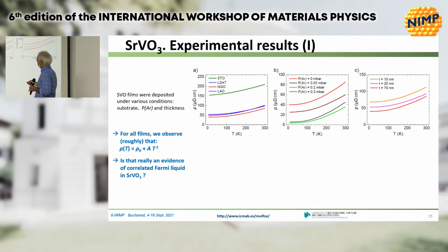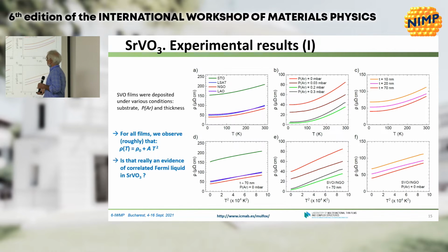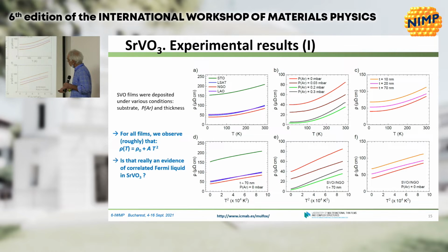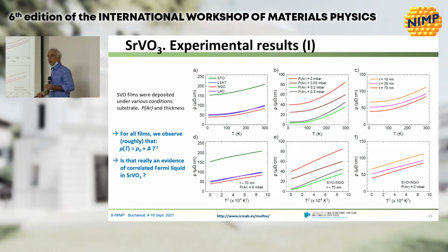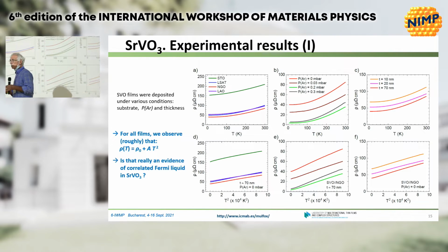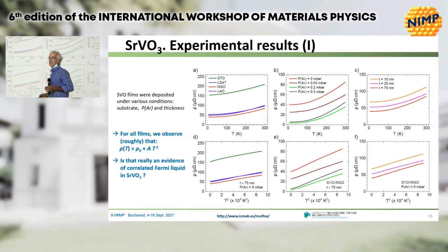This is the resistivity versus temperature of films of a given thickness on different substrates. This is the plot of the resistance on a given substrate as a function of pressure, and this is the plot of the resistivity of the films as a function of temperature on a given substrate and a given pressure as a function of thickness. You see that in all cases you have a kind of curvature here, suggesting that maybe a T squared dependence could explain the data, and that is what a plot of resistivity versus T squared shows. It's more or less linear, but obviously the fit is not perfect. But this is the standard result, and those are the fingerprints that people take of the electron-electron scattering in metals. So let's see what we can learn from that.